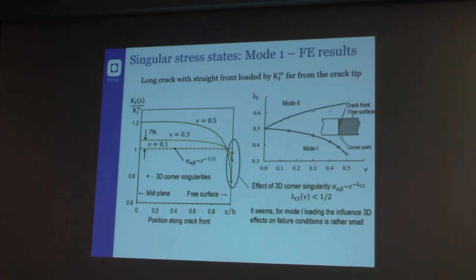So of course this is half of the plate, and this is changing a lot if you are considering a small value of Poisson's ratio. If you have a Poisson's ratio of 0.1, which is the case for some ceramic materials, the sensitivity is very small and you have almost a straight line. If you have 0.3, you have a difference between the mode 1 solution and the two-dimensional mode solution of 7%.